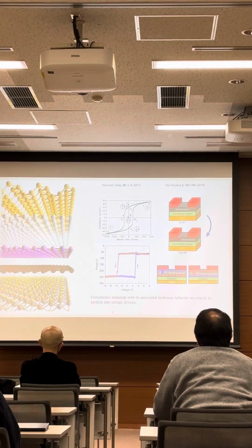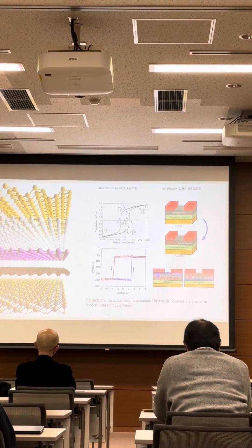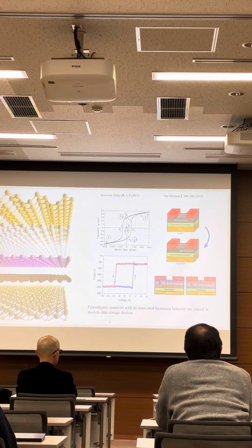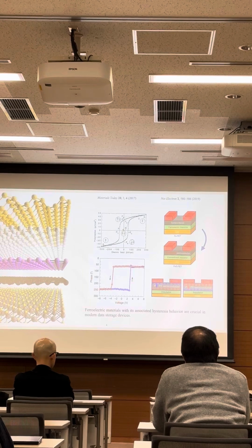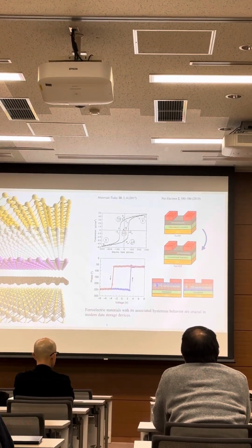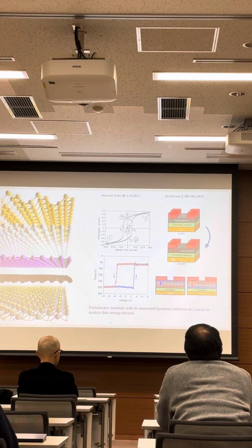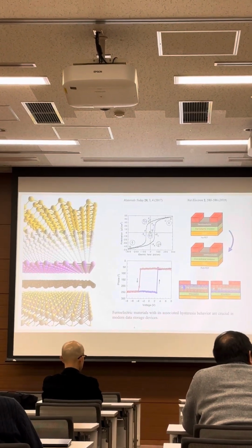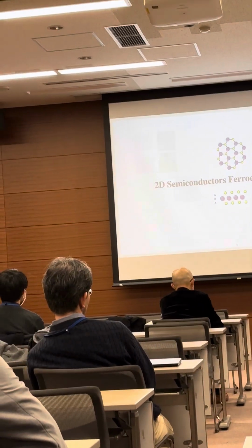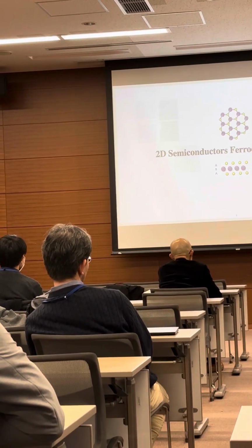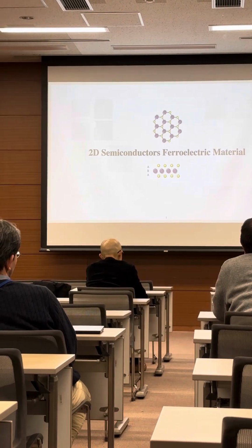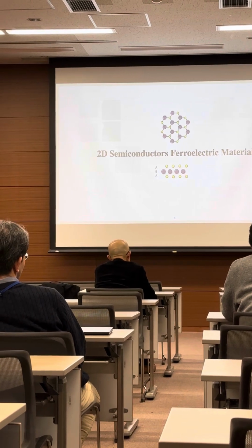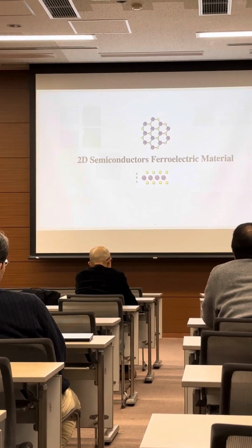So with the rapid increase in demands for data storage, it's no surprise that there is a strong desire to reduce the dimension of these ferroelectric devices by exploring new materials such as 2D semiconductors like this one. The problem is that in the case of 2H-based TMDs, the preserved central symmetry directly results in incompatibility with ferroelectricity. Therefore, development of these devices has just been stalled for the past few decades.